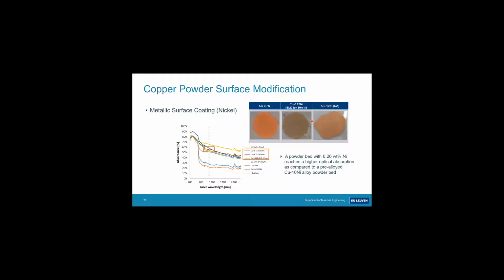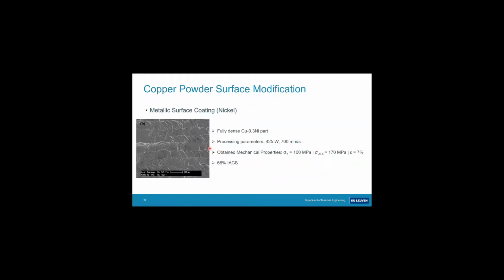And this is, by the way, as a reference, a pre-alloyed gas-atomized copper 10 nickel powder. So you see that a powder with an overall content of 0.26% nickel already looks much darker as compared to one with 40 times as much nickel content, but homogeneously mixed in the powder. And you also see that in the absorption behavior. So you see that a coating layer, in this case a few tens of nanometers, drastically increases the absorption from this level to this level. So for the powder absorption, this was certainly beneficial.